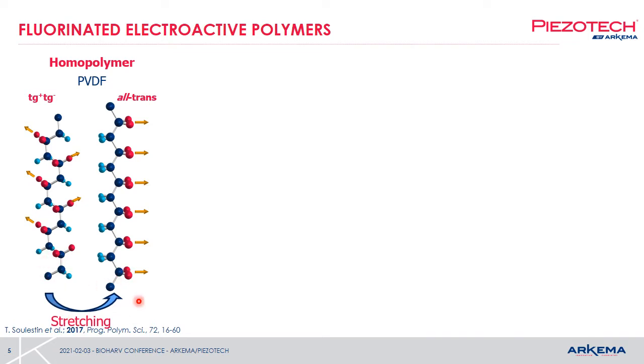You need stretching. So if you need stretching of a bare film, it means that you cannot print these films, and also these stretchings introduce, let's say, an instability of the film. So if you heat up a stretched PVDF film up to 80 degrees C, the film will shrink and you're going to lose the piezoelectric properties.